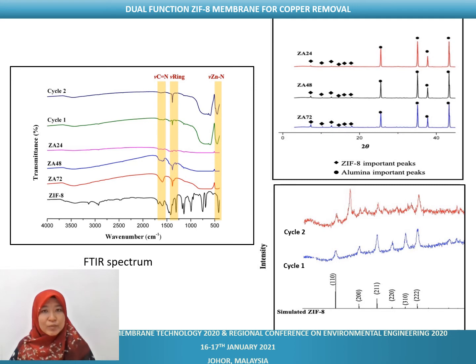All the membranes with APTES modification prepared at different reaction times also showed the same characteristic XRD reflections. ZA72, the ZIF prepared at 72 hours, shows the highest intensity among all, indicating that the longer reaction time produced a ZIF-8 membrane with better crystalline structure. While the membranes prepared via layer by layer show characteristic ZIF peaks, they have rather lower intensity compared to the prior method. Comparing one cycle and two cycles, the two-cycle membranes have more intense XRD peaks than the one-cycle membrane. Therefore, it is noted that the number of cycles affects the peak intensity.